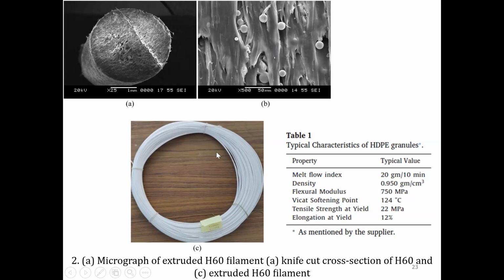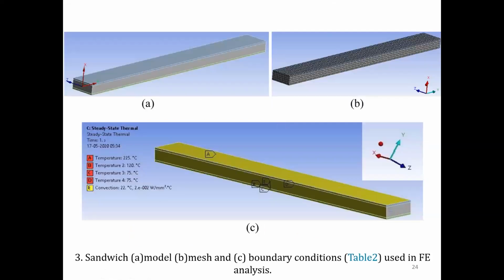Now, the extruded H60 filaments you can see here, and typical properties of HDPE granules, which we bought from Indian Oil Corporation Limited, are mentioned here for your reference. Then we did the sandwich part, and we took the help of finite element analysis. As we all know, the sandwich structure consists of a skin, upper and lower, and the core, the middle portion. The printing parametric optimization was carried out for the core first, being thicker. We need multiple printing layers there. The filaments have the composition of, as I mentioned earlier, H20 to H60, fed to a fused filament fabrication-based 3D printer.